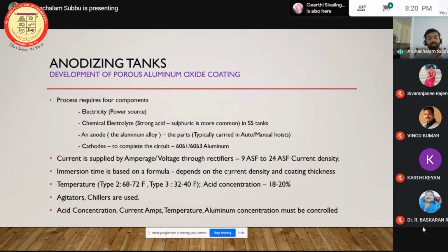And there are also other parameters like temperature and concentration, which you have to maintain. Chillers are used because the temperature has to be maintained in a certain range, like 68 to 72 degrees Fahrenheit for type 2. So for that, you'll be using a chiller. And there will also be an agitator to mix the solution in the anodizing tank. All the parameters like temperature, aluminum concentration, and acid concentration should be controlled.